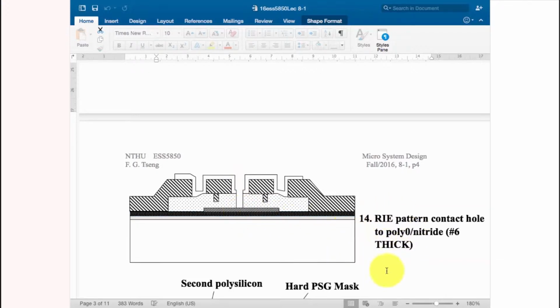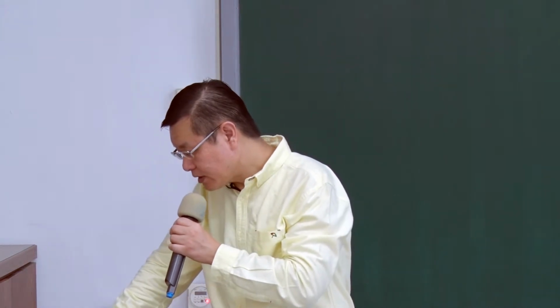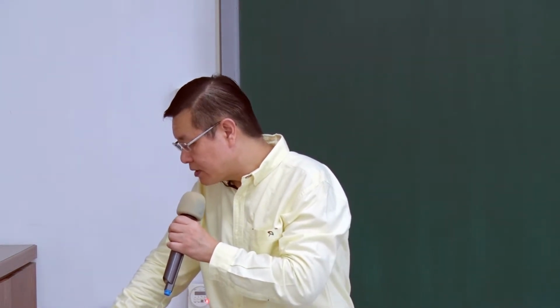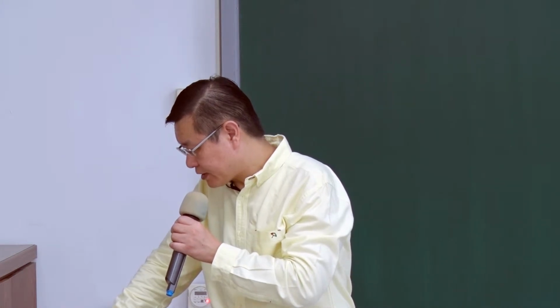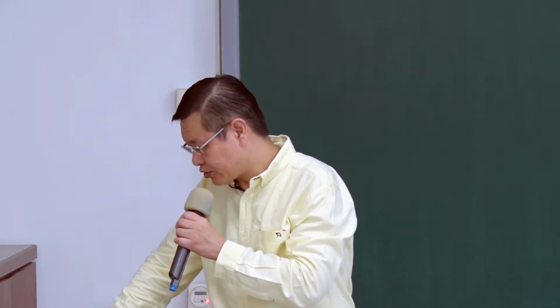After you apply the thick layer etching command, remember, there are two etching processes here. One is the thin layer etching. The other is thick layer etching. Thin layer is for only cutting through the second sacrificial layer, but the thick command will cut through the second plus the first one together. So you get an overall connection from the very top to the very bottom for the thick layer. And after that, you can deposit the second polysilicon layer, the structural layer.